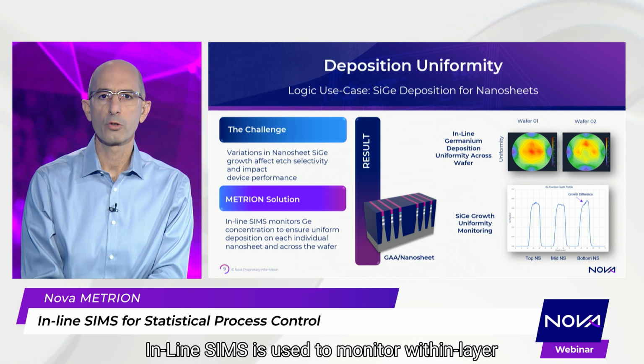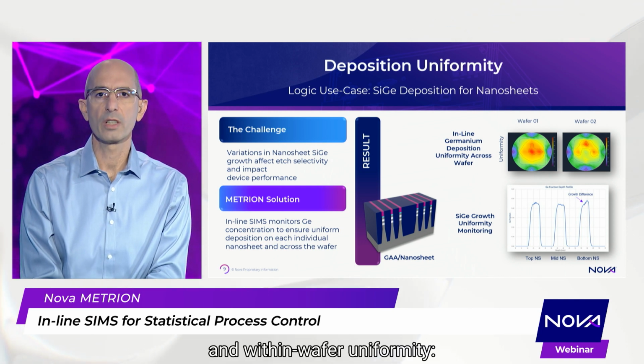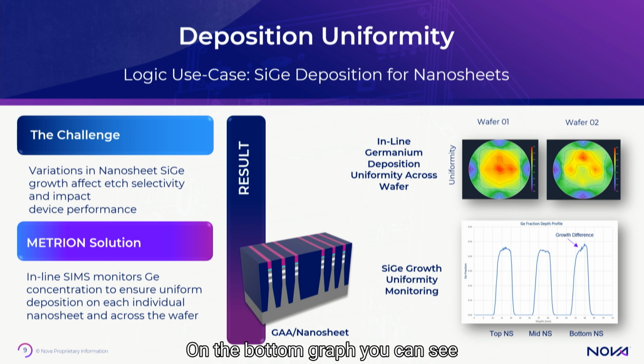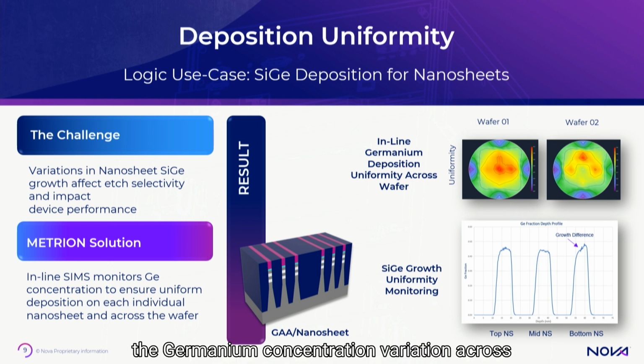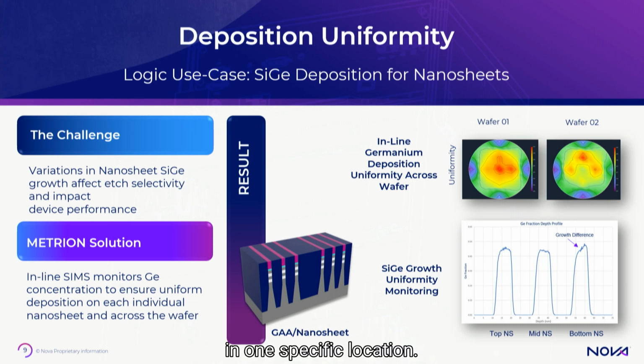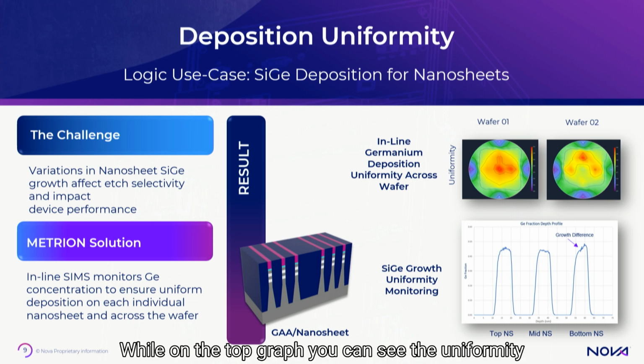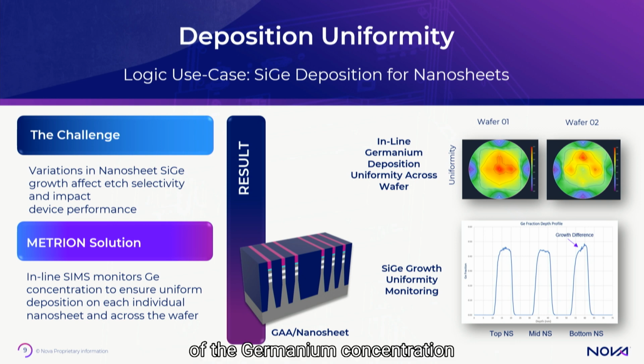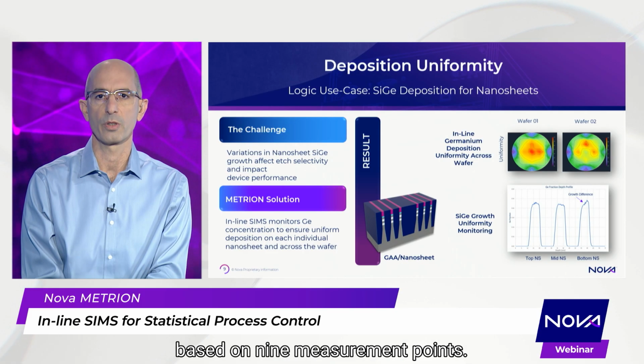Inline SIMS is used to monitor within-layer and within-wafer uniformity. On the bottom graph, you can see the germanium concentration variation across each one of the 3 individual nanosheets in one specific location. While on the top graph, you can see the uniformity of the germanium concentration across the entire wafer based on 9 measurement points.